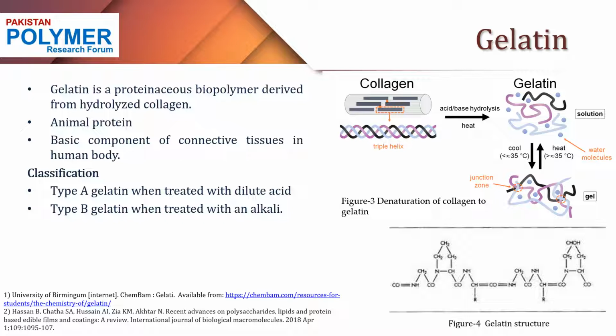In gelatin, there is a sol-gel temperature of roughly 35 degrees centigrade. This is the central point where gelatin can be converted into a gelatin solution or a gelatin gel. If we heat it above 35 degrees centigrade, water molecules will be incorporated within the chains and increase the free volume, and the gelatin will be converted into a solution. But if we cool it below 35 degrees centigrade, the polypeptide chains attached by hydrogen bonding will try to regain their triple helix structure and form a gelatin gel. Rather than converting back to collagen, it is an intermediate, reversible stage where the hydrolyzed gelatin can convert from gel to solution or from solution to gel depending on the temperature.